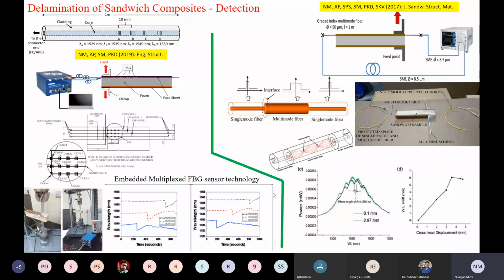This capturing of the delamination is also very interesting, because usually you cannot see the delamination from the face of it, because it is happening inside the material body. So capturing delamination is also very troublesome. What we did in that case is put in different types of optical fibers. The diameter of the optical fibers is very small, so you understand that it is a very small thing that you are embedding within the material. Then you pass light, and as you apply load, there is a change in the frequency of the light being transmitted. With the change in light frequency, you can find out the strain that is being developed in the material. So that's what we are doing here.